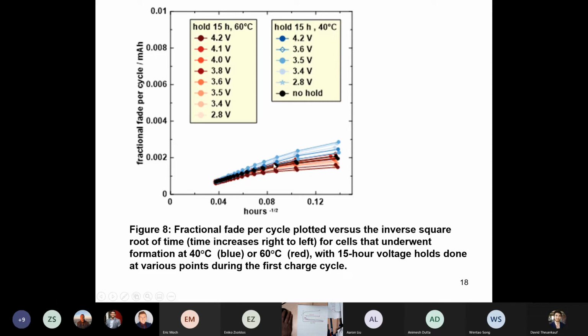But then over time, and this is many, many hundreds of hours to get over here, everything ends up reaching the same point, because the SEI growth at 40 degrees C, where all this testing is done, they eventually all come to basically the same point. And there you can extrapolate these back to zero, because you're following this t to the minus half law. And it looks like no matter where you start, you're always going to end up with a cell that's going to die at the exact same rate. So the reason to do this type of thing at the beginning is so that the customer in the early cycles sees a very small capacity fade rate, but it doesn't affect the long-term cycle life of the cell.